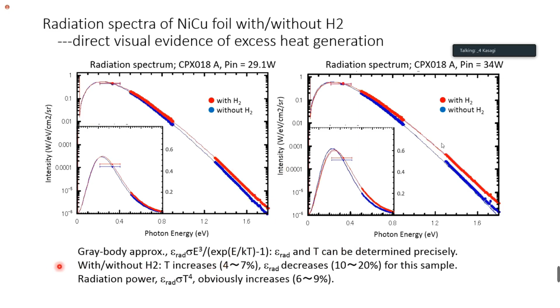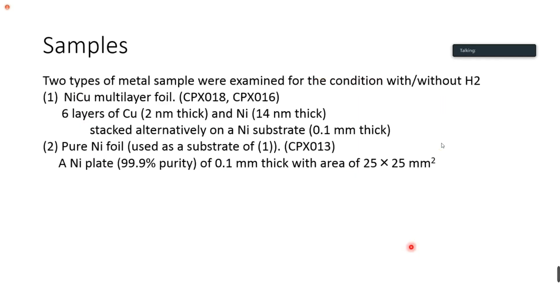And this is just general: if you compare with hydrogen to without hydrogen, usually temperature increases 4 to 7%, but emissivity decreases 10 to 20% for this sample case. So this is not negligible, but we are very safe. Even if this decreases, we know that the radiation power is increased because this is just a direct measurement of this one.